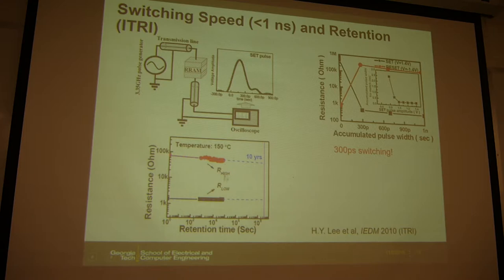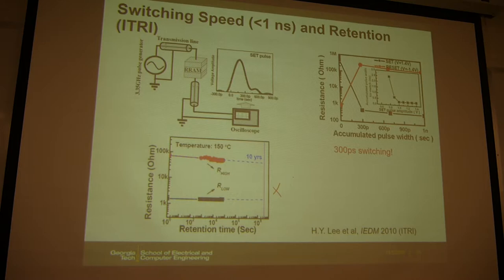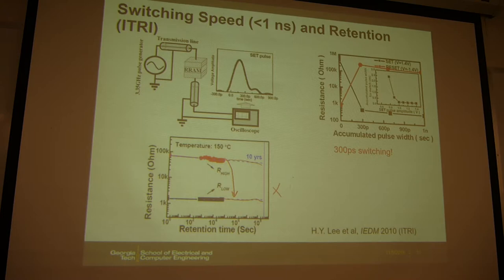For data retention, since this is non-volatile memory, baking experiments were performed — reading resistance as a function of time at high temperature. The approach shown in this paper of simply extrapolating to 10 years is not good, because failure may happen differently. This is not the best way to do retention testing, and better methods have been discussed.